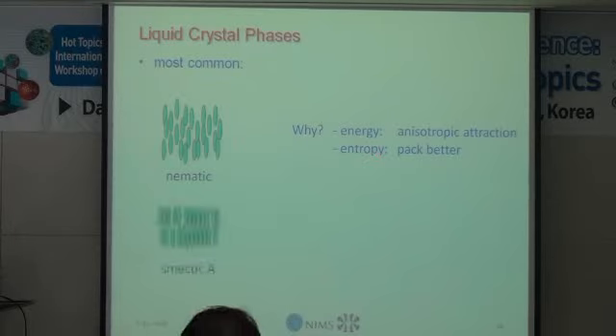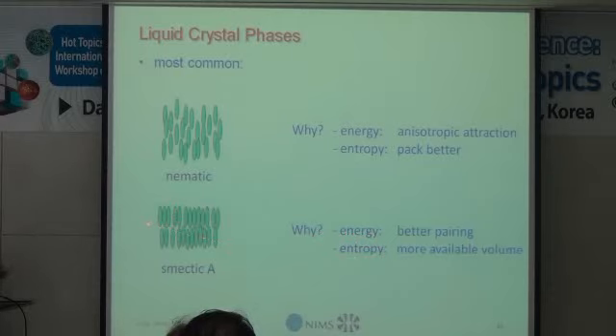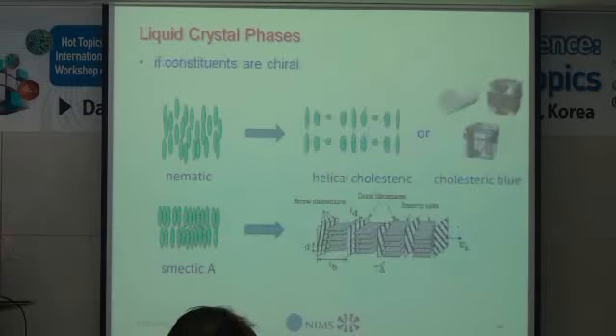Smectic phases are layered phases, and again, both energy and entropy prefer this layering in certain regions of parameter space. So interestingly, if you take hard particles with no attractive interaction and you pack them into space, they will form a layered structure, which might be a bit surprising at first. All right.